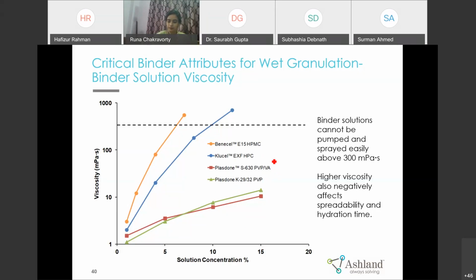But coming to Klucel, there is an advantage of particle size: instead of making a binder solution, you can use a finer grade. You can mix it in the dry mix and do granulation with water. When we make a binder solution at lab scale, it is different from the binder solution we make at production level, because the quantity is too high and there are chances of lump formation. So it is always recommended to use dry binder and do granulation with water, because you can reduce one manufacturing step of the formulation in production.